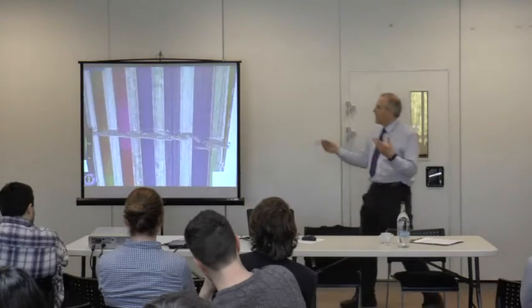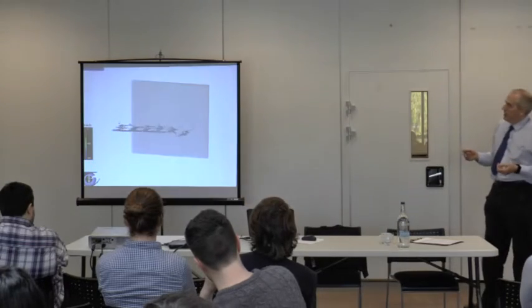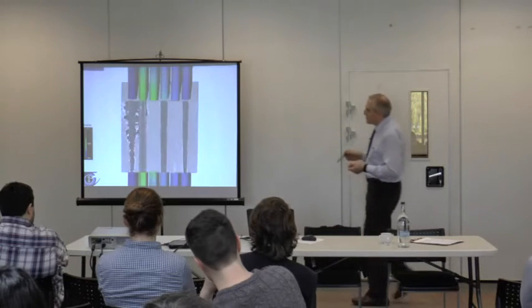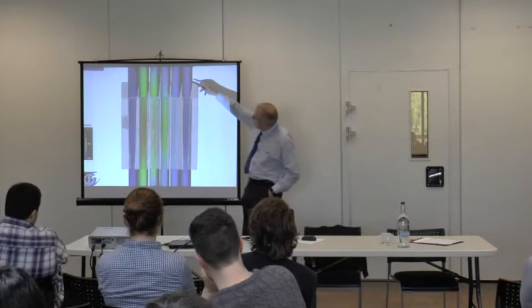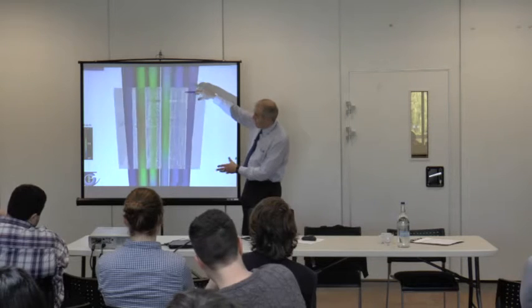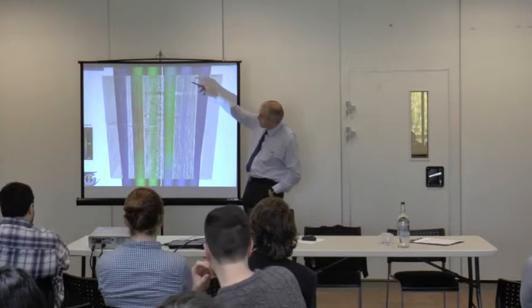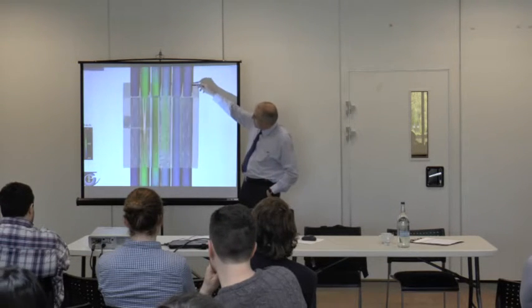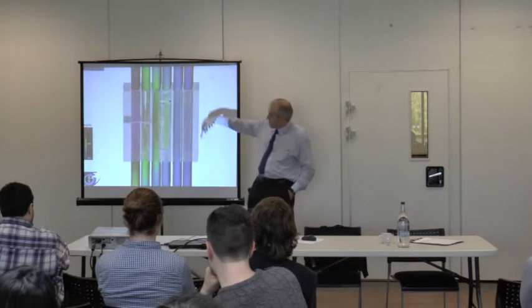Other things we can do, combine tomography with the lattice strain stuff. So this is silicon carbide metal matrix composites. This is a real sample as well. They took, this is Phil Withers and Co. That's done at ESRF in Grenoble. So these things are about 100 microns diameter, silicon carbide fibers.